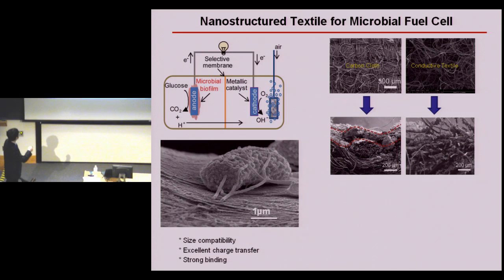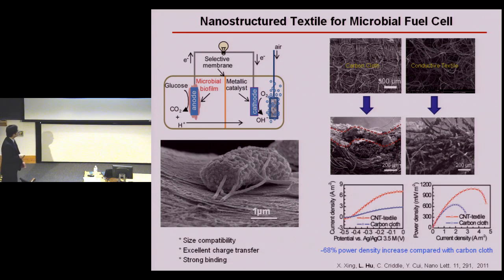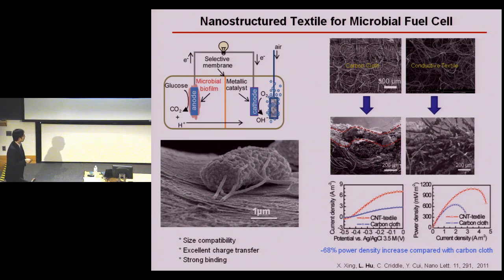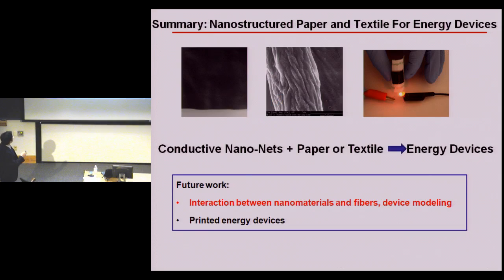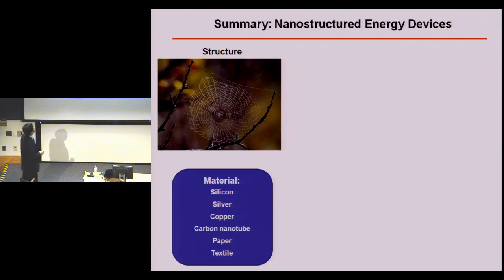This is the interface between the bacteria and the conductive textile surface. These are the nanotubes, and these are the bio-nanowires from the bacteria. Because of this size compatibility, we achieve much higher power density compared with the current technology, which is based on carbon cloth. So this is the summary for the third part. Basically, I showed you how we can combine conductive nanonets with paper or textile fibers to fabricate highly porous conductive paper or textile, and we opened a whole range of energy device applications.